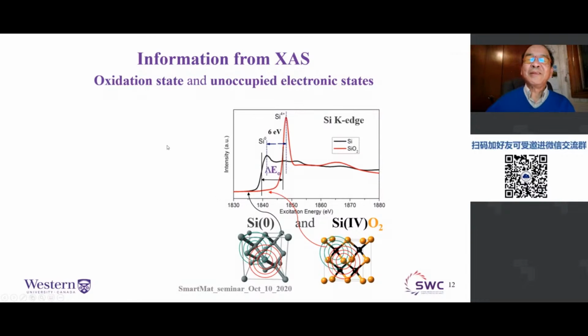Okay, so one of the obvious parameters, of course, is the shift of the threshold. It's very obvious that Si4+ is at higher energy because it requires more energy to pull the electron out, because some of the valence electrons are gone, so they don't get any screening. So this is the chemical shift. This is information you can get.